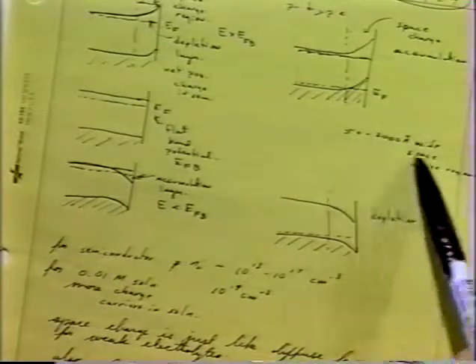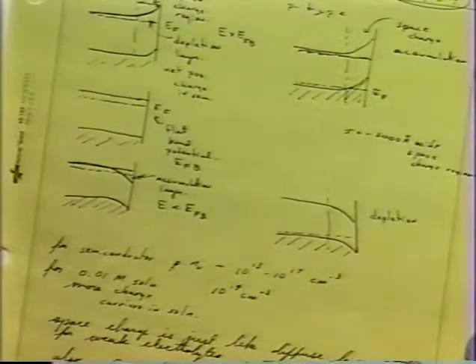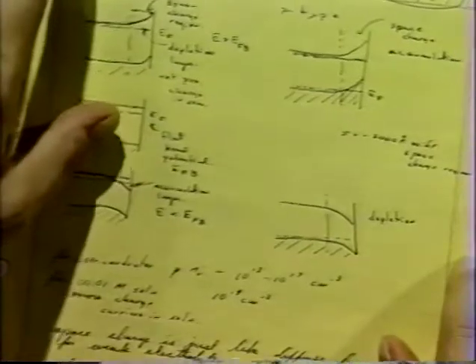What's that space charge region? It's about 50 to 2,000 angstroms wide, and in many respects, it's a lot like the diffuse layer in an electrolyte. Remember, we talked about the diffuse layer having some physical size, and the smaller the number of ions we had from our supporting electrolyte, the more that diffuse layer extended out. And that's a consequence of the Poisson-Boltzmann distribution of ions. As we decrease the number of ions, the statistical distribution of those ions is going to be more spread out.